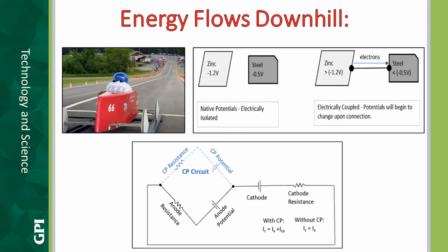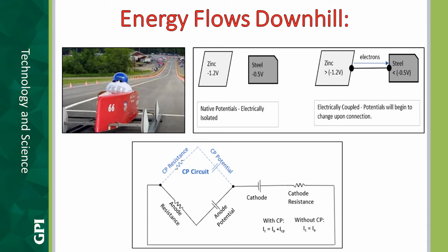Energy flows downhill, right? Energy will flow from a high energy material to a low energy material. This is a fundamental principle in corrosion and is also, by the way, the second law of thermodynamics. This is illustrated using the very common zinc anode connected electrically with steel. If they're unconnected electrically, both the zinc and steel samples will release electrons to the environment and both will corrode. However, if they're wired together, the higher energy zinc electrode at a native potential of minus 1.2 volts will flow electrons to the steel, which has a native potential of about a half a volt. So energy is flowing downhill.